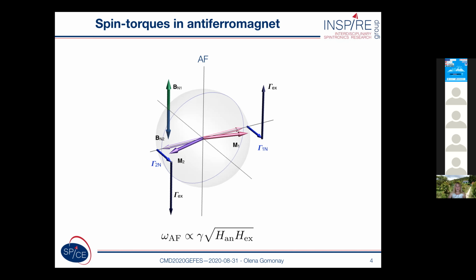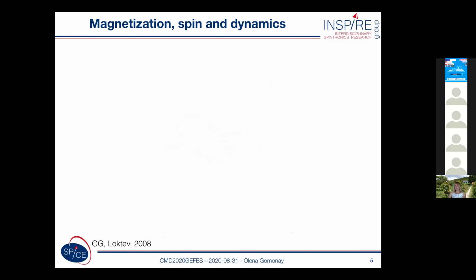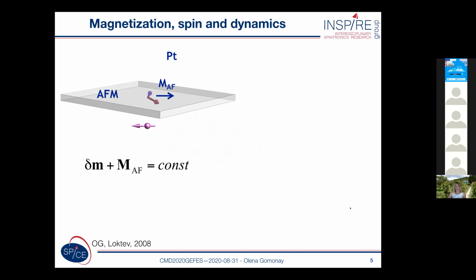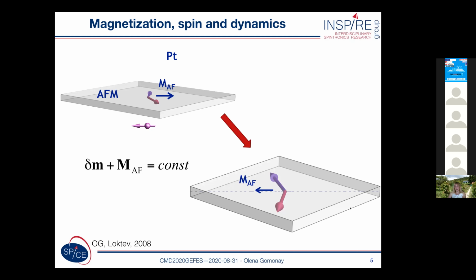and description of the antiferromagnetic materials. So magnetization is related with the rotation of the magnetic sublattices. So this means if for some reason the antiferromagnet can absorb the spin, which comes, for example, from the platinum layer, this additional spin creates small magnetization, so it induces canting due to the spin conservation law. And then this non-zero magnetization induces fast magnetic dynamics. This also means that the magnetic dynamics in antiferromagnets can be considered as the dynamics of these small magnetic moments.